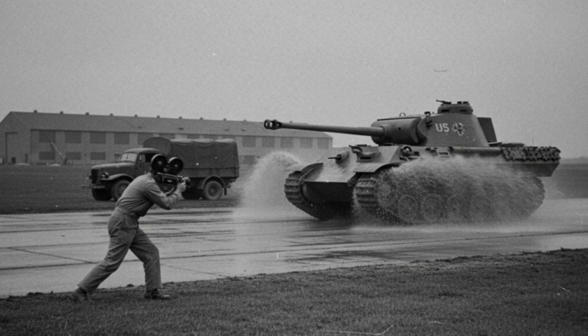thicknesses under 90 mm." Nevertheless, welds displayed sulfur inclusions and occasional porosity, likely due to oxygen scarcity in late war production. The Army also evaluated German design philosophy as expressed in the Panther's sloped armor geometry. Using a specially constructed mock-up, the ballistics branch measured the effective thickness of the 55 degrees glacis. The formula, actual thickness divided by cos angle, gave 80 divided by cos 55 degrees equals 139 mm equivalent line of sight.